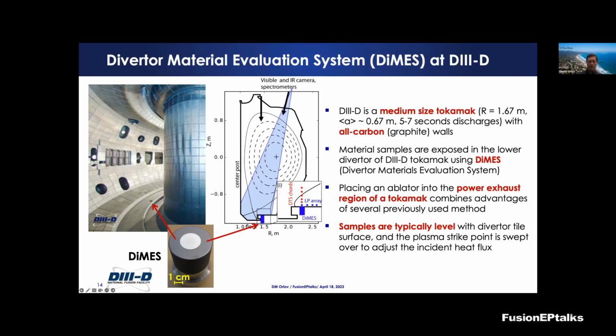It is a nice way to introduce different material samples in the lower divertor to hot tokamak plasmas. We usually place an ablator flush with the surface for the PMI experiments. We have a nice view of this DiMES port, and we can change the materials that we expose literally between the shots. We need about 15-20 minutes to lower the DiMES head, replace it with something else, put it up, pump it down, and run the next shot.